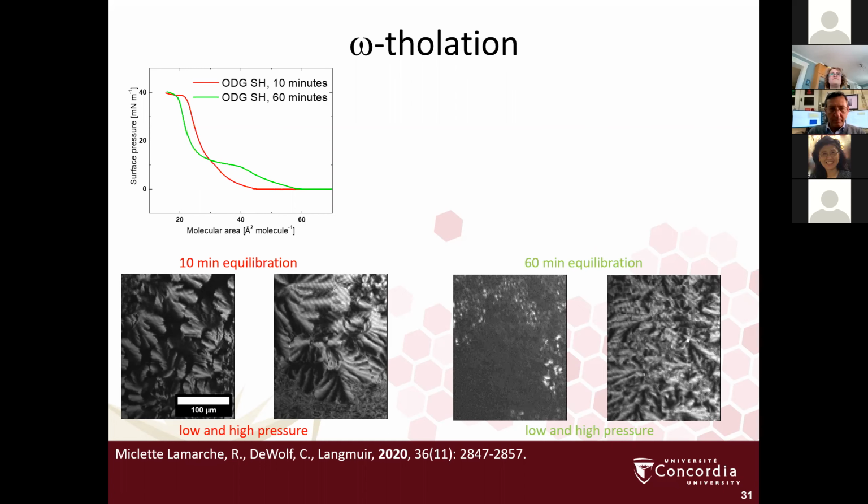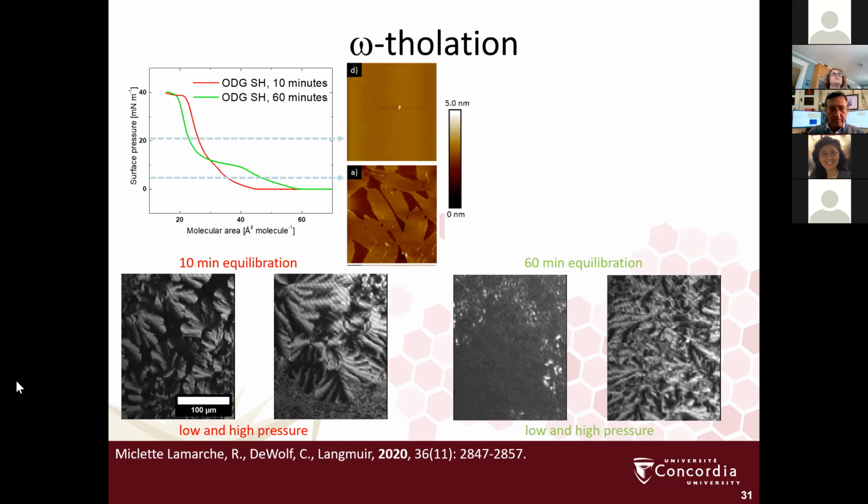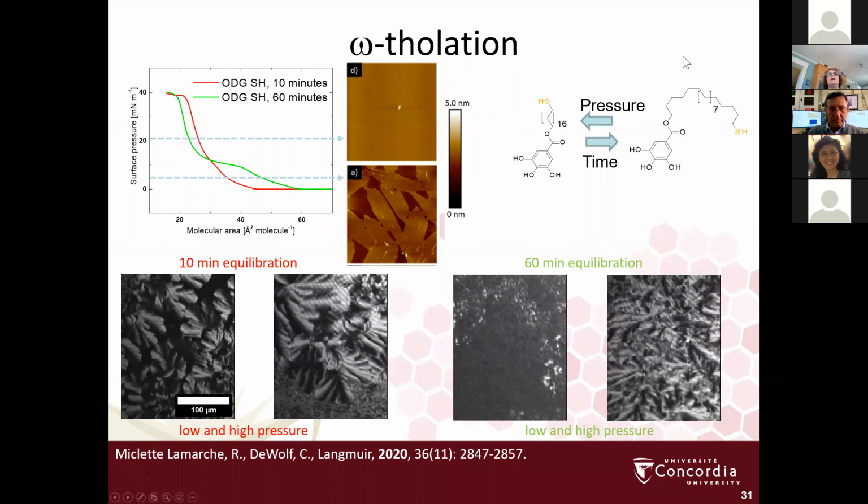And the height difference from AFM corresponds, again, we can push this to a homogeneous phase above this plateau, and we have domains below the plateau, and that height difference coexists very well with the coexistence between a BOLA form and an extended, which appears that over time it can relax. We can control this. So with time, it relaxes more to the BOLA conformation, but with pressure, we can force it back out of that and into an extended conformation.